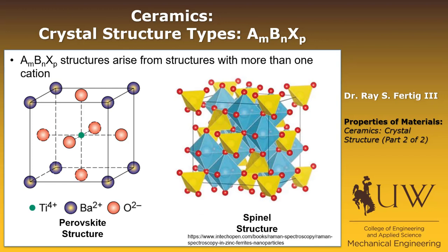I'll give you a final, even more complicated look at what's called a spinel structure, comprised of three elements. The anion is oxygen — those are the red atoms. Inside the blue octahedrons are iron ions, and inside the yellow tetrahedrons are the zinc ions. So this is actually a zinc ferrite structure, and many other structures adopt a spinel structure as well. This is just an extremely small subset of the possible structures that are out there.